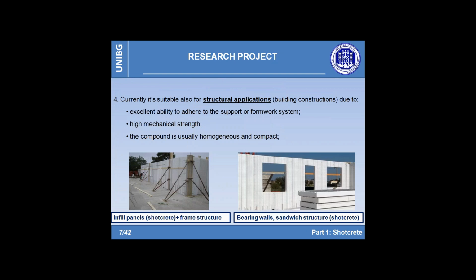In the first figure on the left, for example, the structure is composed of moment-resisting frames made of traditional concrete, while the infills are made of shotcrete directly applied on the EPS panel that operates both as thermal insulating material and as formwork for the shooting. Differently from the previous, other more standardized construction processes use an integrated system based on modular insulating panels pre-coupled with a welded wire mesh and finished by a concrete casting. In this case, reported on the right corner, the building bearing capacity is given by sandwich walls obtained using the previous reinforced EPS formworks as a support for the shotcrete application. It's important to note that in this system it is essential to ensure structural continuity between the individual modules by providing constructive measures such as the insertion of supplementary reinforcement or the overlapping of the wire meshes.